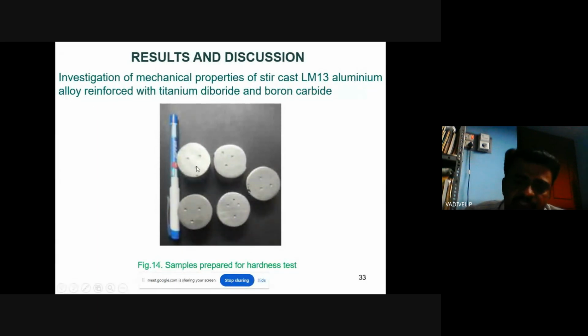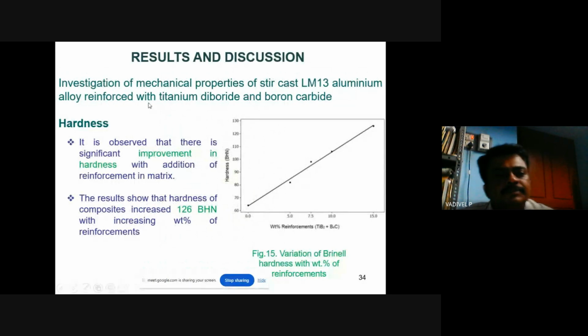So these are the specimens with varying diameters. For the microstructure, the specimen is very small, and for the hardness testing, the sample is a little bigger. Then this is the hardness test. The improvement is compared with the LM13 aluminum, the LM13 material only, and the new hybrid composite material. It is compared with the weight of reinforcements in the TiB2 and boron carbide.